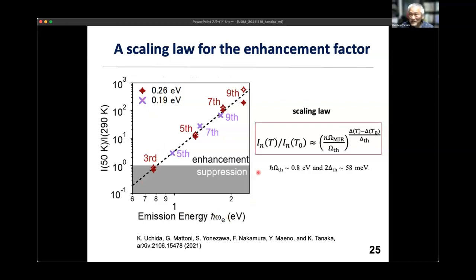This means that we have some kind of scaling law, and this enhancement factor can be given like this. So delta is the gap energy of the system, and T0 is this temperature. So the gap energy difference should be the power of this intensity ratio enhancement, and this one is the emission energy, not the order of harmonics. Emission energy is important in this case. This is very different from conventional semiconductor results.